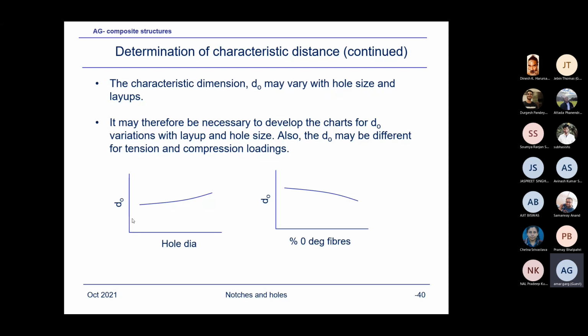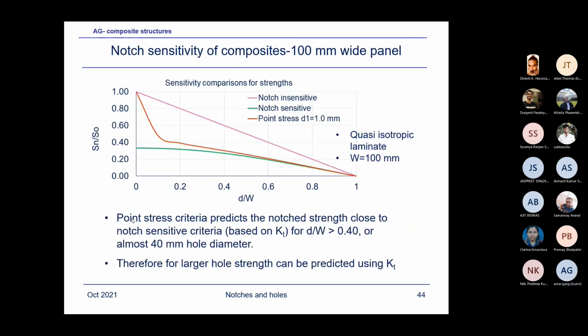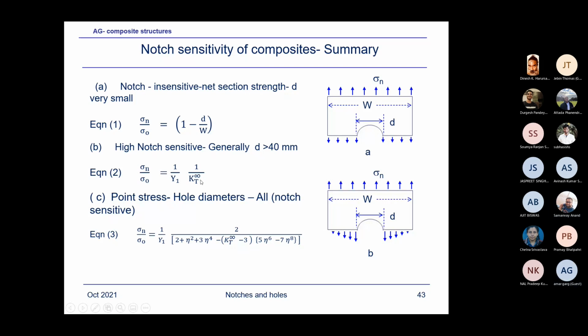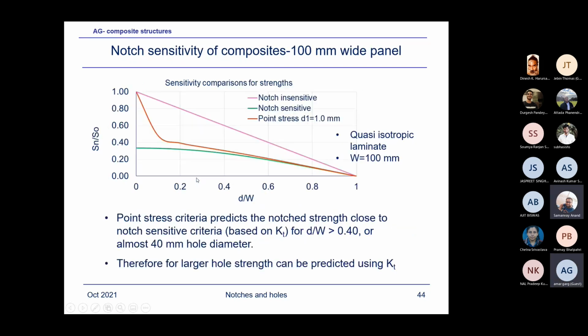And if you have a hole size greater than about 40 millimeter, as you said, then you don't need D naught. You just use this equation, 1 upon KT, notch sensitivity. As I've shown here, in this region you don't need point stress. You can just use 1 upon KT. Suppose KT is 3. So that means 1 upon 3, that is sigma naught by 3, is your residual strength for the hole. Simple. Thank you, sir.